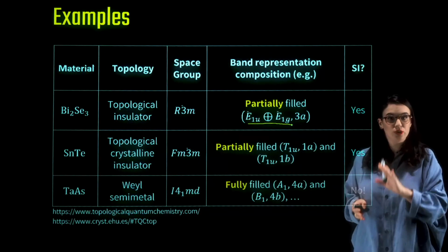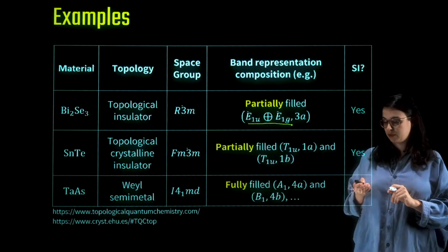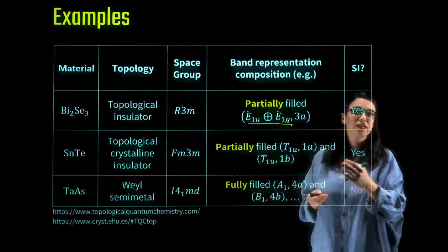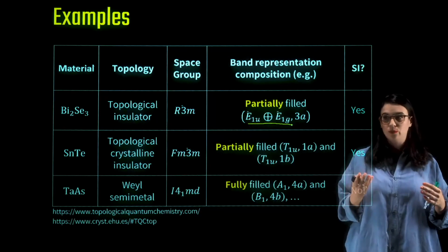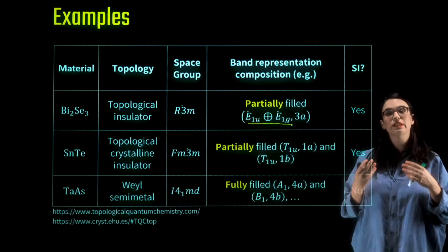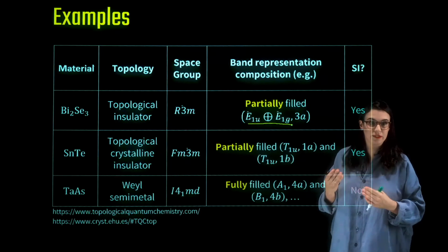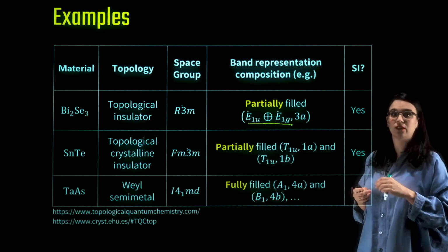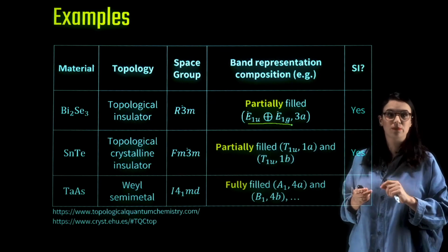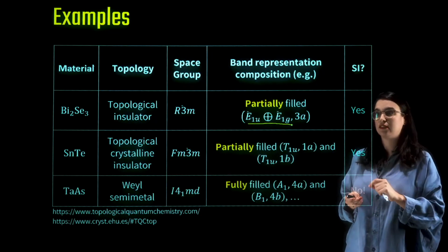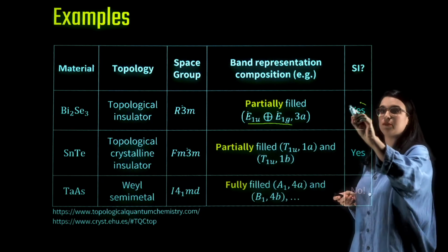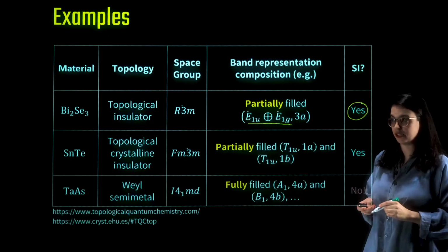That is not a unique combination. There are other possible combinations. These representations, one will come from bismuth and one will come from selenium. And we will need spin-orbit coupling to see this band inversion. So the fact that it's possible to determine just from symmetry eigenvalues that it is not an atomic insulator means that, yes, indeed, it is symmetry indicated.